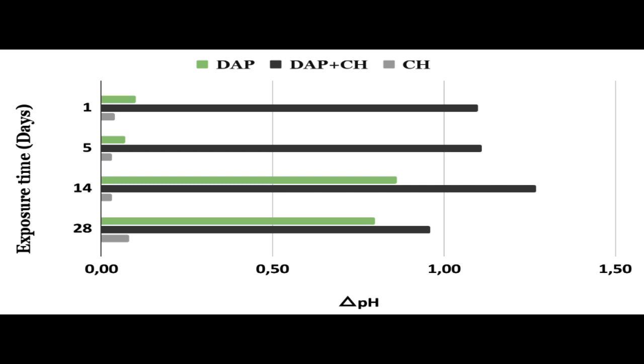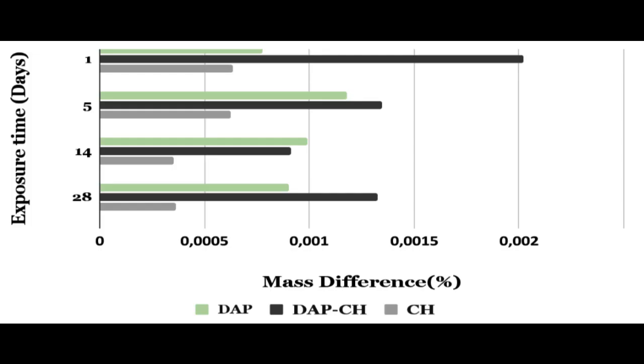In pH analysis, DAP and DAP plus CH solutions show no significant change in pH levels during the first 2 exposure ages. However, on day 14, both solutions experience a slight pH difference, followed by a stabilization. In contrast, the CH solution did not show abrupt change, maintaining stable pH levels through the exposure time. Mass change analysis revealed variations over the exposure time due to the mineral deposit generation and eventual solubilization of them.